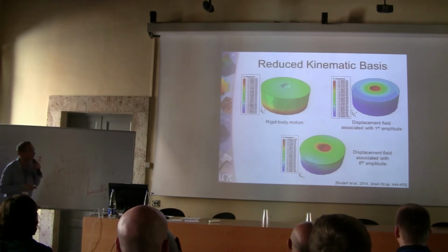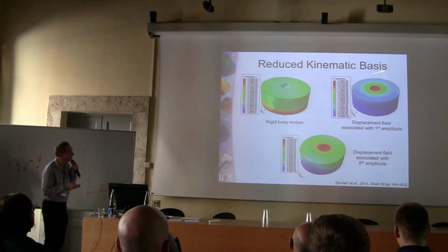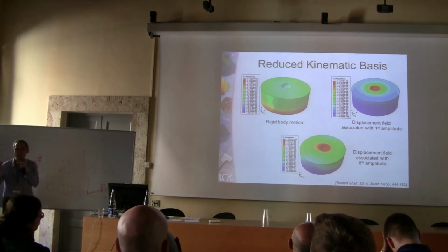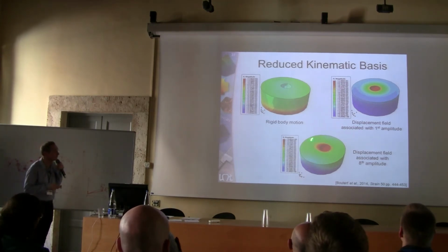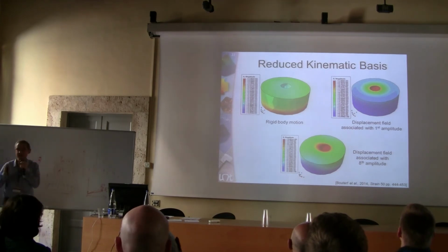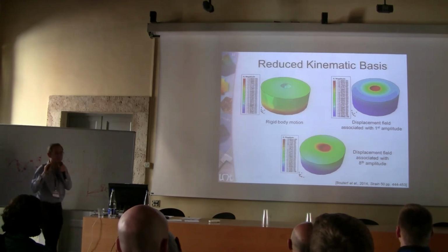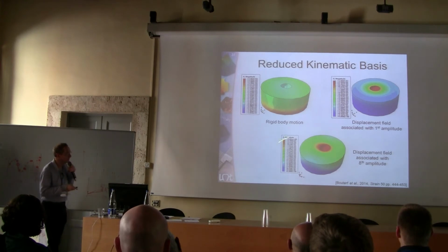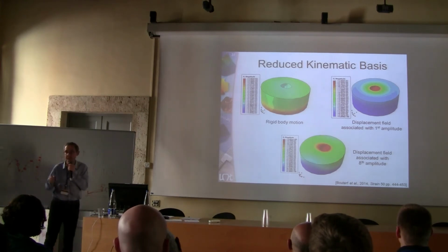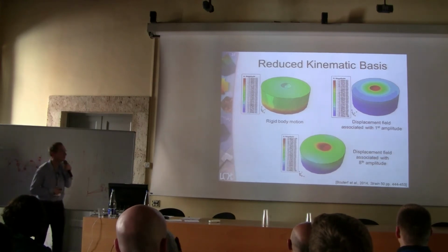What turned out to be important is obviously the dominant mode, which is the one we would expect with indentation, but also two transverse modes that are due to the fact that the experiment was not perfect. These two modes turned out to be critical to really minimize the gray level residuals.